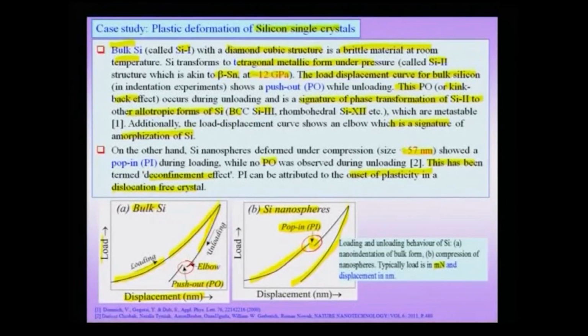It should be noted in such experiments that the load is typically in the millinewton range and the displacement is on the nanometer scale. So, these are all very sensitive experiments done on silicon nanospheres with a lot of care, and you try to see how the deformation of a nanosphere is different from that of bulk silicon. You do see a difference when you do such an experiment, and the significant difference is in the loading stage of the curve.